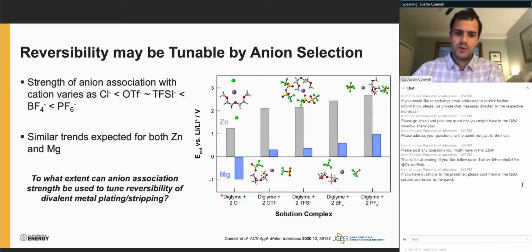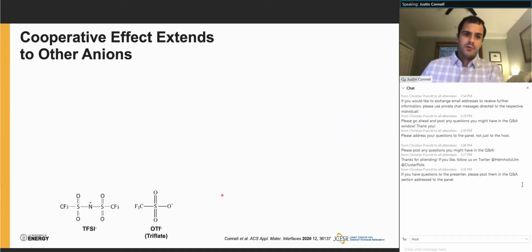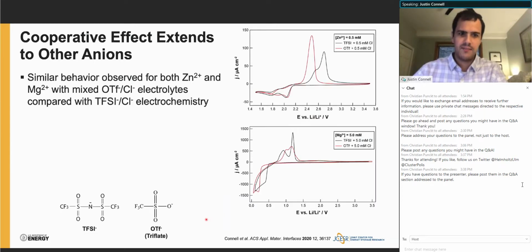So we want to know, to what extent can anion association strength really be used to tune the reversibility of metal plating and stripping? And so we begin by exploring a chemically similar anion to TFSI, this triflate anion shown here schematically on the bottom left. What we see is that for both zinc and magnesium, we see very similar behavior for both the mixed TFSI chloride and triflate chloride systems, where the magnesium more or less looks identical, where we see 2 oxidation features and 2 reduction features in direct analogy to what we saw with the zinc system.